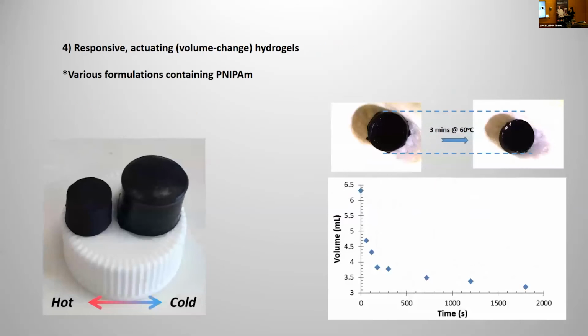That was really good. Now, because these gels, these ionic gels, contained poly-NiPAM, as I said, for the covalent network, poly-NiPAM is a gel which, when you heat up, it shrinks. And then when you cool it back down in the presence of water, it swells up again. So we're able to make these reversible actuating gels. And because there are carbon nanofibers in there, we're able to perform joule heating. So you didn't have to submerge it in a bath of hot water for it to do this.